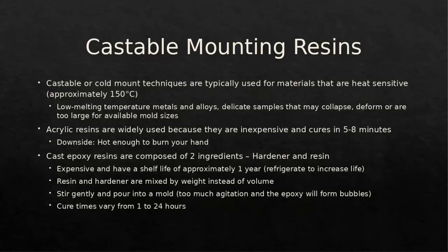sensitive. So low melting temperature metals and alloys, anything delicate that may collapse under pressure or deform, or maybe the samples are just too large for any available mold size that you have for hot mounting, then your castable mount would be the way to go. The least expensive and very quick material would be your acrylic resins. These typically cure within 5 to 8 minutes, and you're able to use the sample, after it cools down, probably 15-20 minutes afterwards. But the downside is that it's hot enough to burn your hand, so you're not going to be able to just handle it the moment it's fully cured.